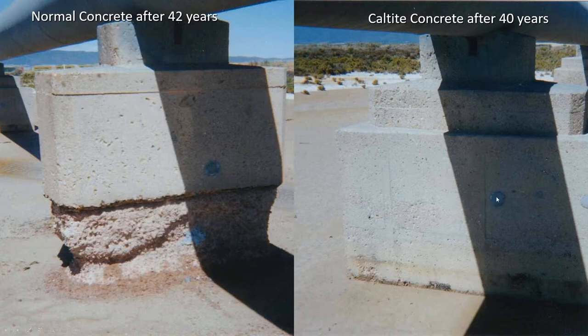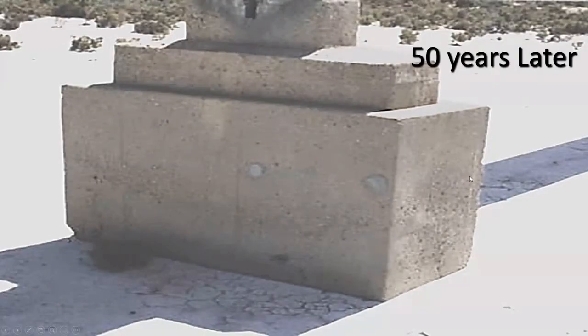The other interesting thing they noted from the cores when they took them out, these cores went straight through one layer of reinforcement. And it was noted that the reinforcing steel was still in pristine, as new condition after 40 years. And that is the latest photograph I have, that's after 50 years. Concrete is still fine, still serviceable, no sign of corrosion whatsoever.